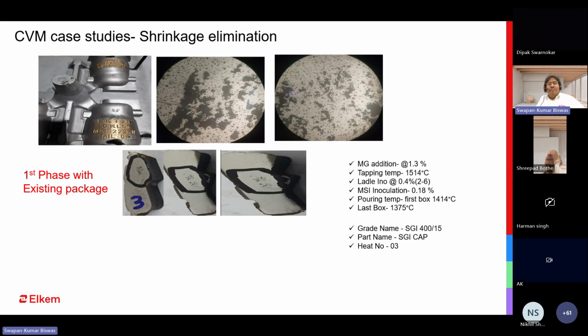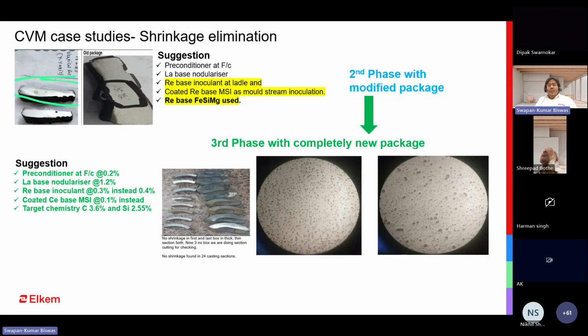Then on the basis of their initial information, we suggested a package. In most cases and case studies, we always recommend a preconditioner, because this is the primary action and it helps to overcome a lot of variation. When your metal health is on the better side, definitely your outcome will be better. So you have to select the type of preconditioner that helps to improve your nucleation sites, and that maintains nucleation till solidification.